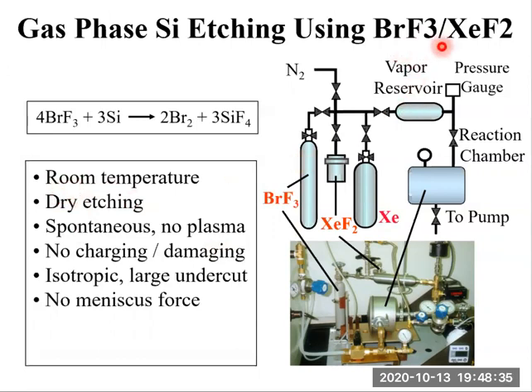Bromine trifluoride or xenon difluoride etching is a room temperature process. It is dry etching, no liquid. It's a spontaneous reaction or etching. It does not need plasma, so no charging and no damage caused by charging. And this etching is isotropic, which is very important, so it leads to large undercut. That's the reason we use this etching to etch the sacrificial polysilicon layer. Since it's dry etching, there will be no meniscus force.